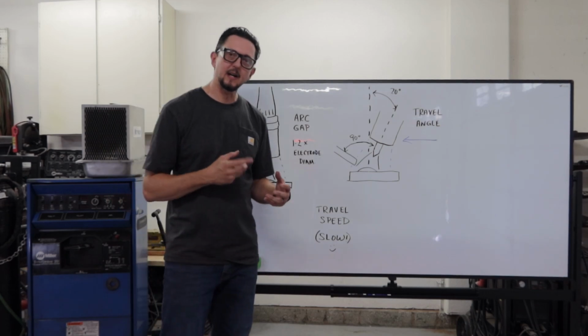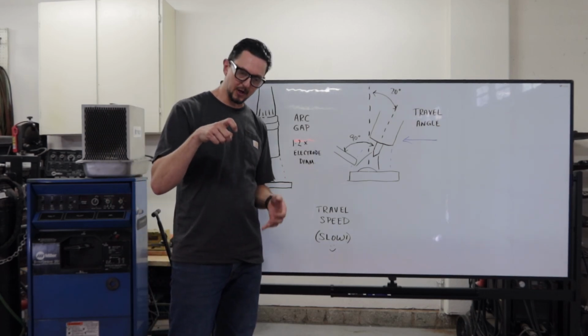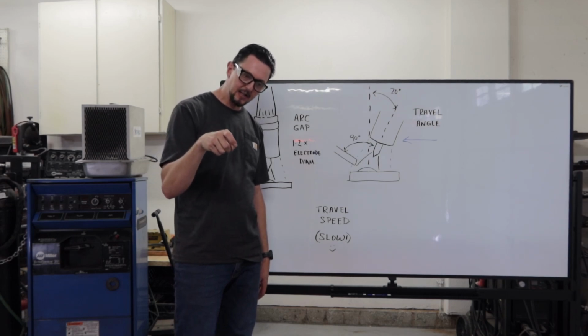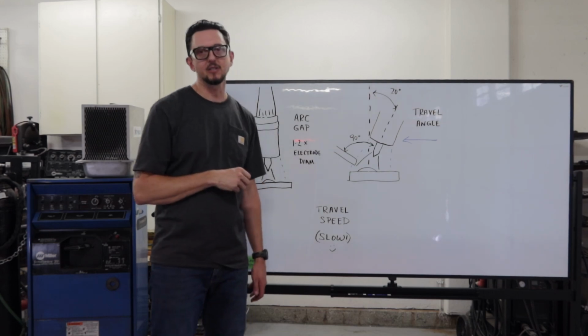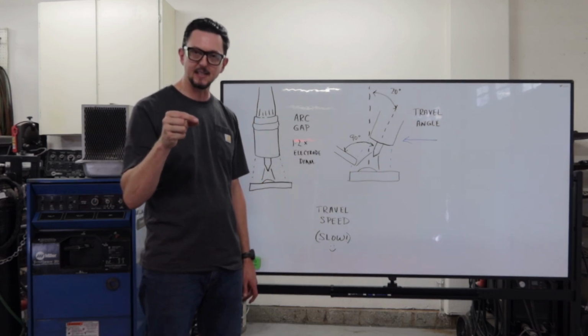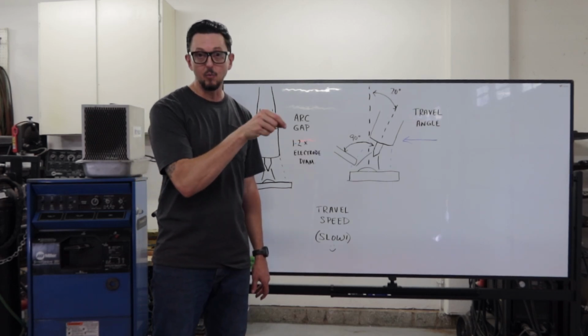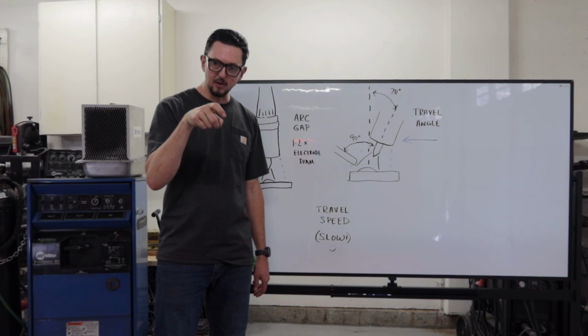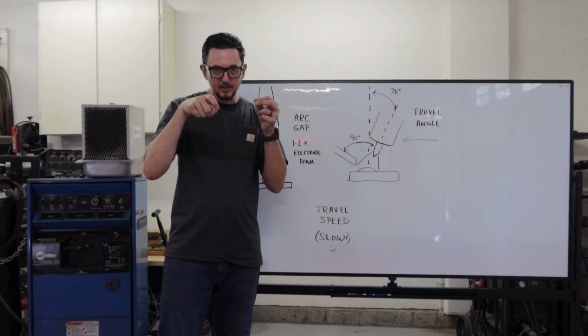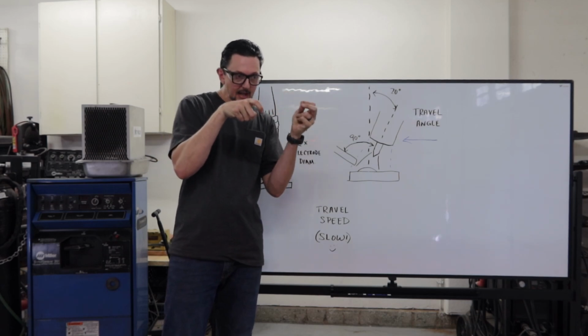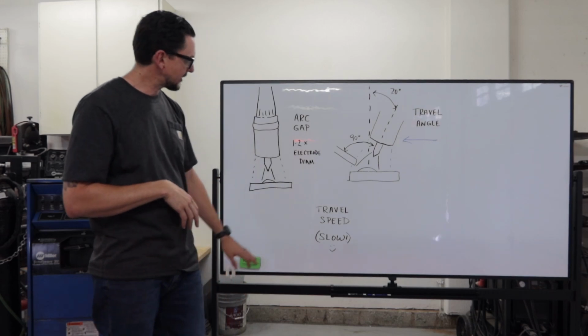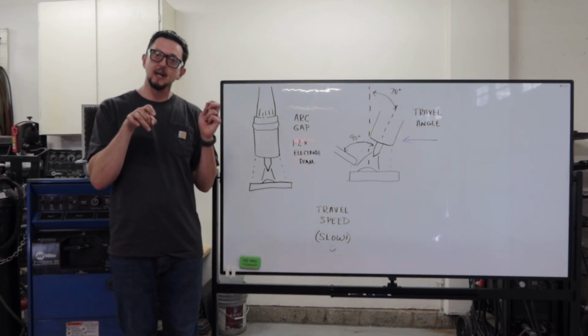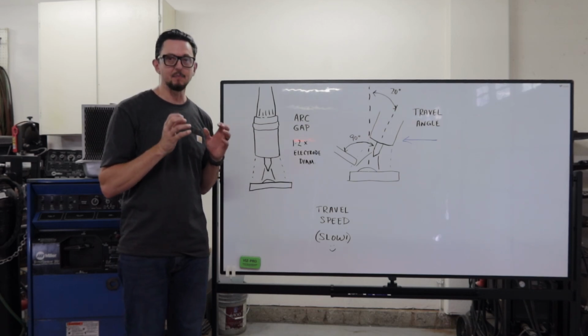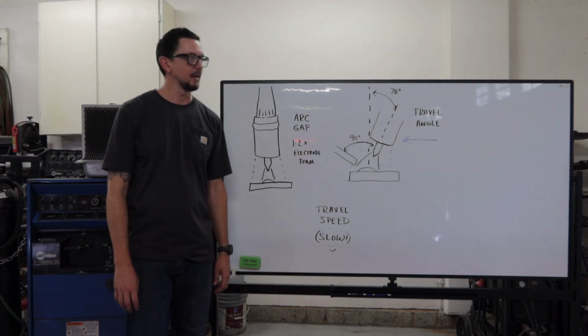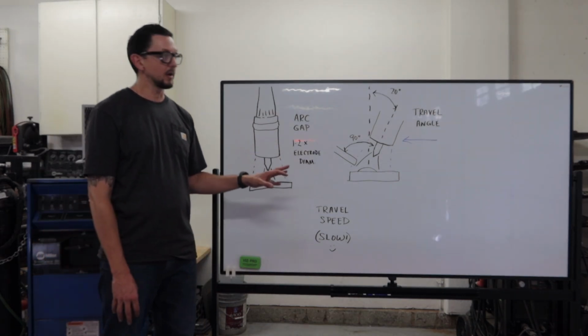Okay, so when you're first starting out, I really do recommend just getting a weld pool started with that nice 20 degree push angle, and just try to push that along the plate to get started. Try to do that consistently and have a consistent size of that weld pool as you go across the weld bead, just autogenous welding with no filler. Then as you get comfortable with that, and you can keep that angle all the way through, you can start to add filler to the front of that weld pool as you go forward, okay? Travel speed slow, make sure you get that weld pool established before you start moving forward, and try to keep all that consistent as you're moving forward. And that is the basic technique for GTAW.